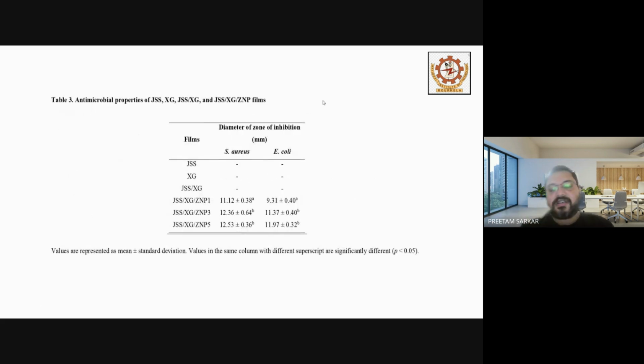And because this is antimicrobial, of course, we're going to target microbes. We're going to use one gram-positive bacteria and one gram-negative bacteria, and target how their antimicrobial efficacy is. As we increase our zinc oxide nanoparticle concentration from 1% to 3% to 5%, you can see the zone of inhibition against the microbe increases from 11 millimeter to 12 millimeter to 12.53, and 9.31, 11.37, 11.97. So there is a significant difference between the control and the treated films.